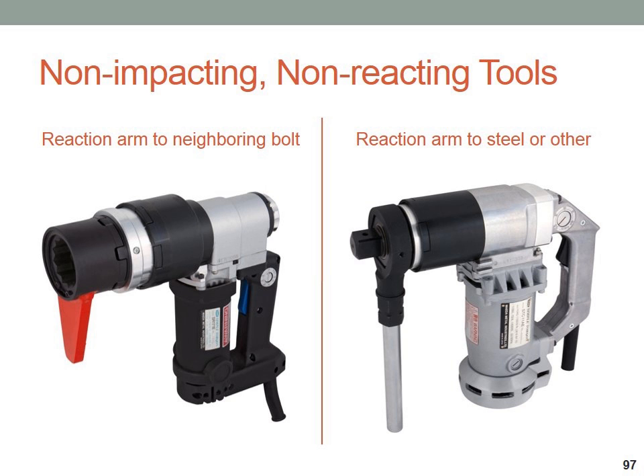There are a number of cases where we have had customers give us a call and say, hey, we're working on this project. We don't even know whose bolts these are, but we're missing the galvanizing on all the corners of the bolts. And they send us samples, and we look at it, and we may send them off to do an adhesion test, find out the adhesion is fine, but it's the severe amount of impacting that causes some of that damage. If you're going to go through the effort to specify the coating, if you're going to have people do oversight to see if the thickness is correct, if you're going to do rotational capacity testing, measure fastener tension, and then have all of that wrecked by having some guy out there just knocking away on it with an impact wrench, it's all sort of for nothing.